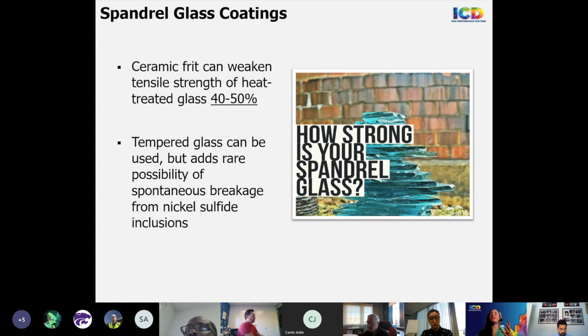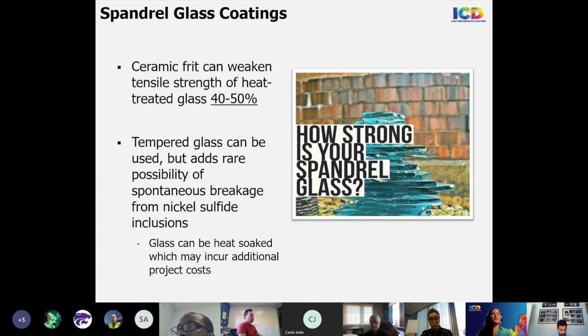Essentially, there's a risk of spontaneous breakage due to nickel sulfide. So when glass goes through the tempering process, nickel sulfide stones can form due to contamination and end up in the center tension zone of the glass. And later, when that glass is exposed to varying temperatures, that tiny stone can grow and cause the glass to shatter spontaneously. And so to expose these nickel sulfide inclusions, glass can be heat soaked in very hot temperatures.